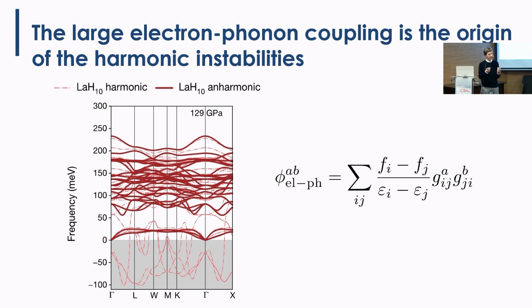And why is that? Why is it not stable in the harmonic approximation? Because if you calculate the harmonic phonons, they have a contribution coming from the electron-ion interaction. What is this contribution? It's like a Lindhard function, weighted by the electron-phonon matrix elements. Basically, this is analytic. This is the harmonic contribution of the electron-ion interaction term to the harmonic phonons, okay? So this means that if you have a strong electron-phonon interaction, and this is negative definite by construction, the contribution is negative definite. So if this is big, the phonons will be suppressed, right? They go down, okay? So the reason why we have huge harmonic instabilities here is because the electron-phonon interaction here is huge, okay?